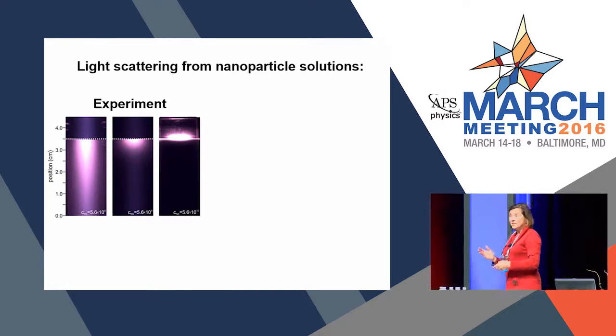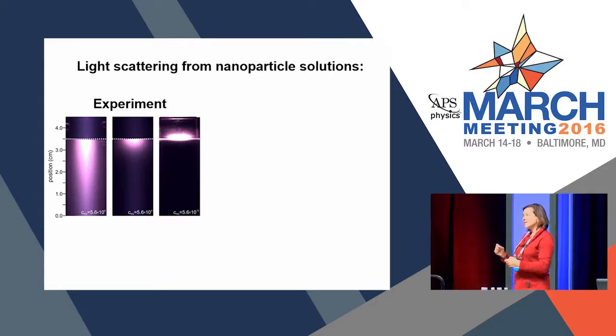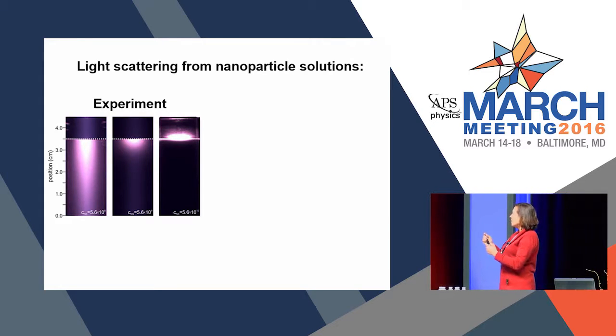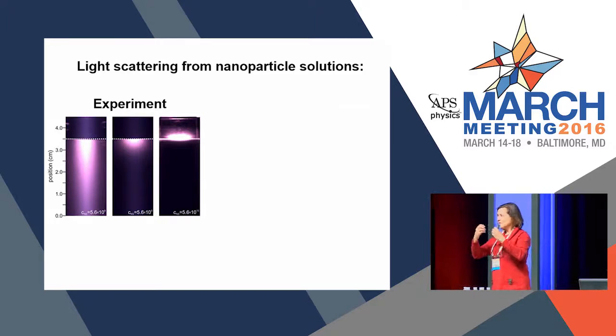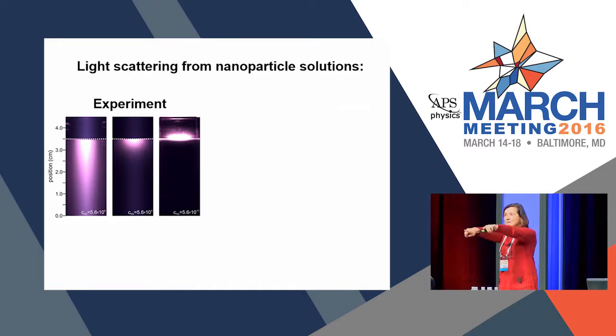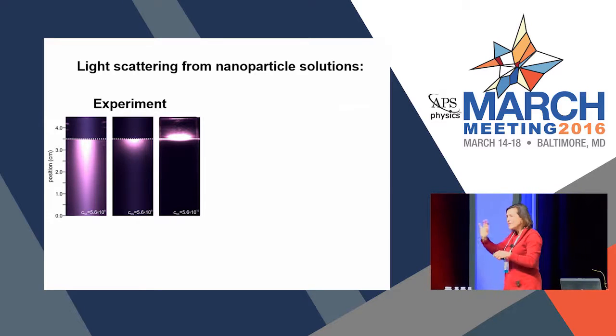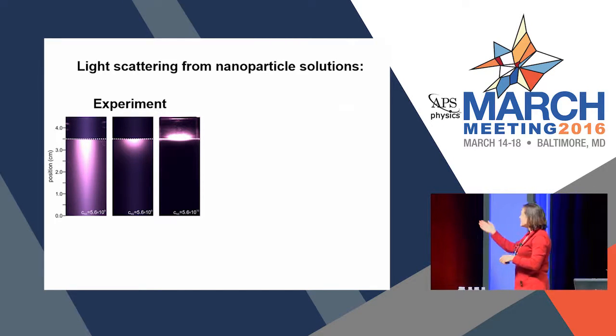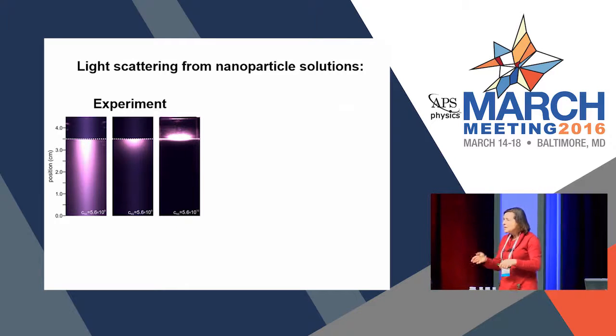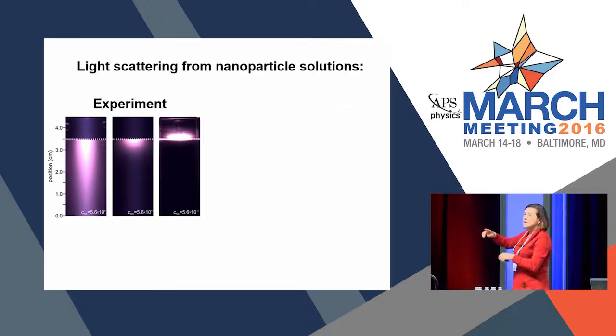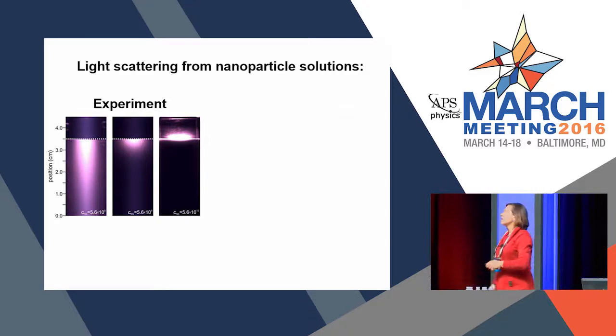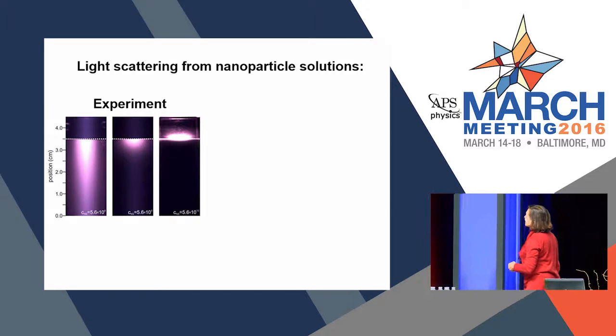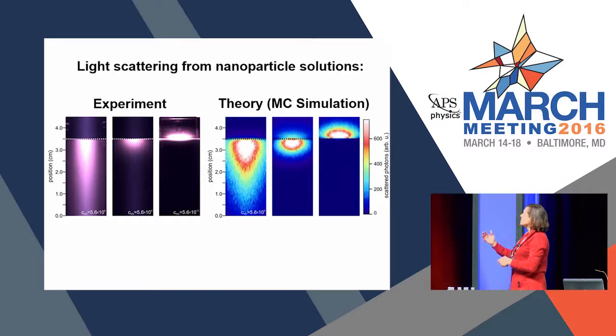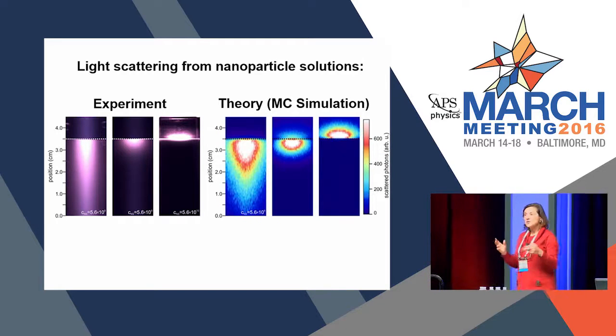Those were simulations, and so we wanted to see how good our simulations were. Rather than simulating where the light's absorbed, we said let's simulate where the light comes out, okay? That means we should be able to go into the laboratory and take photographs of the cuvettes. These are photographs of the 3 different concentrations, and it shows you how different the light energy is. For the highest concentration, we even see backscattering of light out of the vessel. And this corresponds to our simulations extremely well.